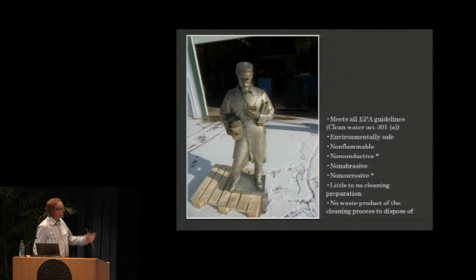So we started looking at CO2 cleaning. We found it was environmentally safe. That's been covered. It's non-flammable. It's non-conductive. By that I mean electrically conductive. Non-abrasive, which we've seen some information to the contrary on that, but in our case it's been very, very non-abrasive. Non-corrosive, I put an asterisk there because if you get condensation, water can be corrosive. But for the most part, the works that we're cleaning, it's not an issue.